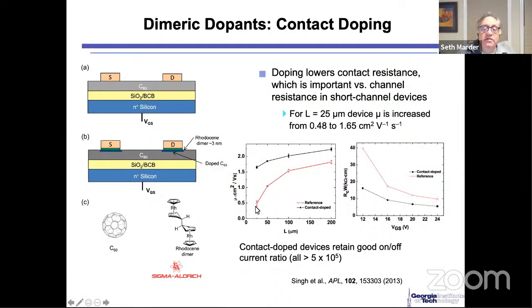And so what you see is that the effective mobility goes from 0.5 centimeters squared per volt second up to about 1.6, 1.7. So it about triples, which is concomitant with the contact resistance, which they extract by doing these transmission line measurements, going down by a similar amount. It goes from 40 down to about 15. So there's about a factor of 2.5 to 3 decrease in the contact resistance, and about a factor of 3 increase in the measured conductivity. And all these materials retain good on-off ratios, which is consistent with the dopant not migrating into the channel.